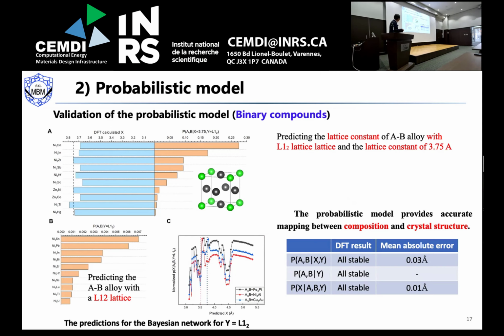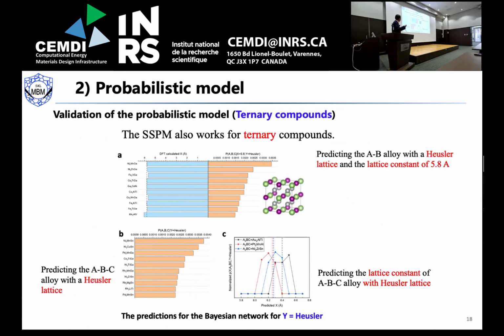But here we show that once you know the elements and crystal structure and predict the lattice constant, the lattice constant error is very small. And the above three are only for binary alloys. We can also do it for ternary alloys. For example, once you know the elements, the crystal structure and the lattice constant, we can predict alloys. This one, nickel, aluminum, and gallium, is a well-known alloy, and also the others which are not well known.